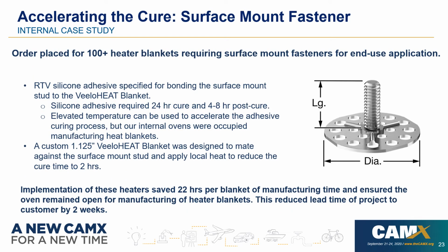So recently we had an internal need to actually accelerate bonding of some surface mount fasteners to our silicone blankets. We received an order of 100 plus blankets that required these fasteners. This is for the customer end use mounting application. We had a requirement for a room temp vulcanizing silicone adhesive. This was specified for bonding the stud to the blanket.